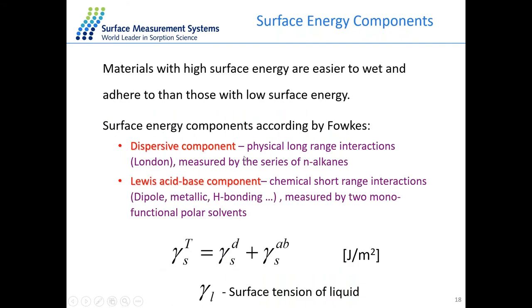With the IGC technique, we can determine the different components of surface energy using polar and nonpolar molecules. For example, we can use n-alkanes, at least three of them, like heptane, hexane, octane, nonane, for the dispersive component of the surface energy. Then we can use two monofunctional polar solvents for the specific component, for example, dichloromethane, ethyl acetate, toluene, chloroform. The sum of the two components gives the total surface energy of the solid material.